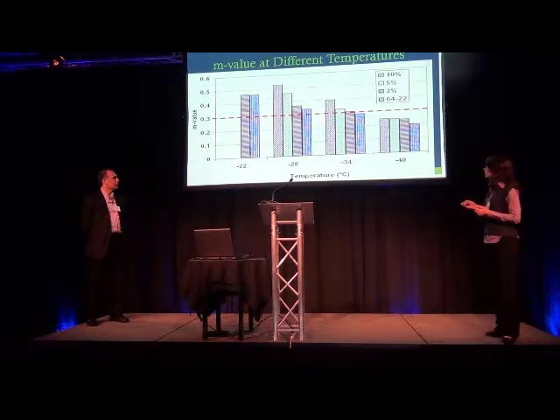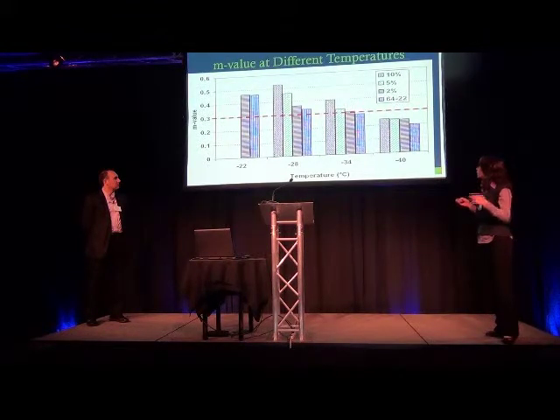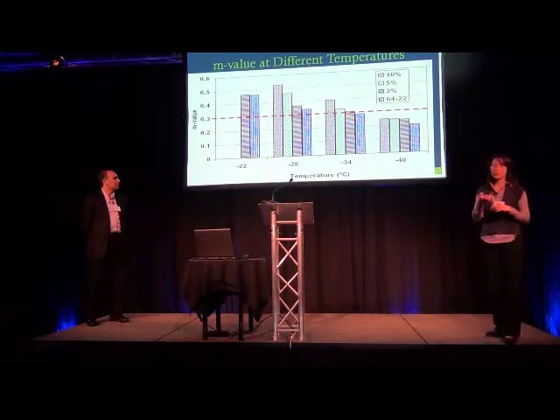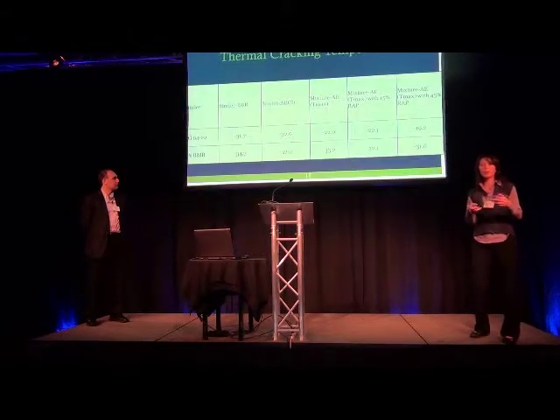But let's look at minus 30 degrees C. At minus 30 degrees C, we have a control here, which is PG 64. This is the asphalt that we use in North Carolina, and in most states except the New England, Massachusetts area, which use another grade. But when you add 10%, you're actually much better in terms of releasing the stress. So with this material, you cannot build up the stress as such. You don't get to the maximum strength of the material, because basically the crack happens when the stress built into the material is more than the strength of the material. If you don't reach that peak of its strength, it's not going to crack.